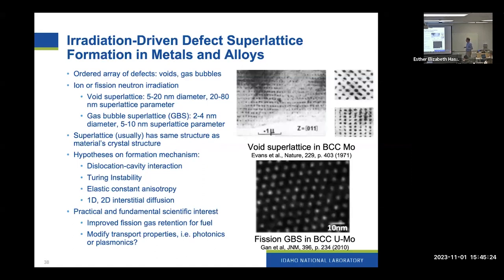What I mean by superlattices is an ordered array of defects, either voids or gas bubbles, depending on how we irradiate them. The void superlattices have a void diameter of usually something like 5 to 20 nanometers, and the spacing between those is something like 20 to 80 nanometers. Gas bubble superlattices tend to be a little bit smaller, 2 to 4 nanometer diameter and something like 5 to 10 nanometer superlattice spacing. The superlattice usually has the same structure as the material's crystal structure.